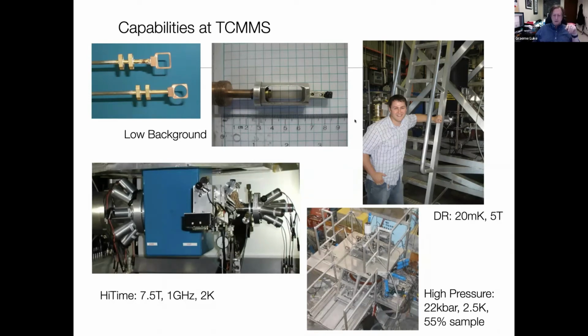So we can go down to experiments as low as 20 millikelvin and fields up to about 5 Tesla. We can go to very high fields, so we can go into about a 7.5 Tesla magnetic field, where the muons will precess at a gigahertz, which is about our timing resolution, which we have to then time all of our events down to about 100 picoseconds. We can also do experiments under high pressure by using high energy muons, where we can go into things like pressure cells and do that kind of experiment as well.